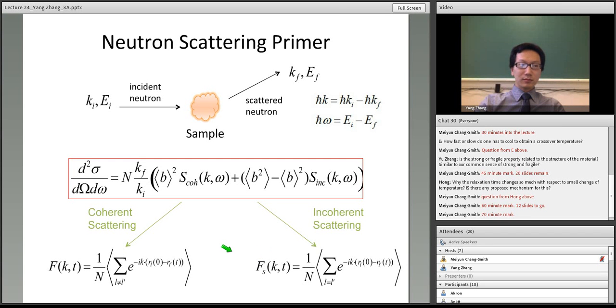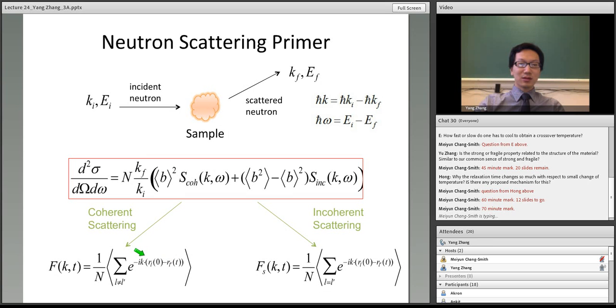So now we can see that what neutron scattering basically probes, the so-called intermediate scattering function, is nothing but a density correlation. They only depend on the number density, so they only depend on the location of the atoms, R_i, as a function of t. And that's the reason why you can easily compare the neutron scattering result with computer simulations, and the test is exactly one-to-one. What we can measure from neutron scattering experiments can be directly calculated from computer simulations.